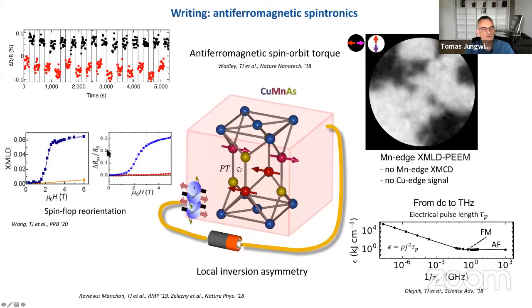And another important confirmation experiment is trying to reorient your antiferromagnetic moments by large magnetic fields. So this is, again, an example in copper manganese arsenide, where you can have spin flop reorientation between 2 and 4 Tesla. And you see a resistivity change, which is comparable to what is seen in these electrical switching experiments.